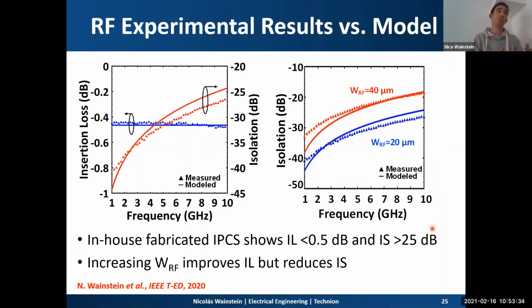Also, the way we managed to overcome some of the fabrication process issues was to have overlap contacts, which limits the performance at very high frequencies. Up to 15 gigahertz, you will have pretty good insertion loss and isolation. Beyond that, the parasitic capacitance between the RF contacts and the heater will be dominant and can limit the performance. But again, it depends on the application and what you would like to sacrifice between insertion loss and isolation. Still state-of-the-art performance, but there's a trade-off there.